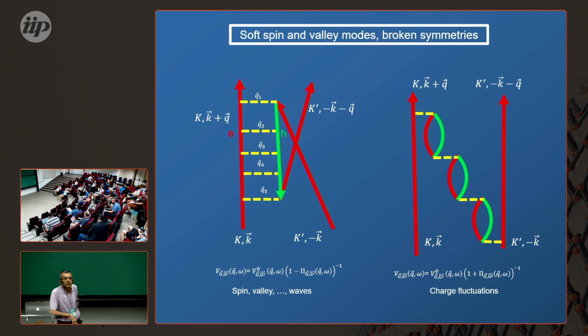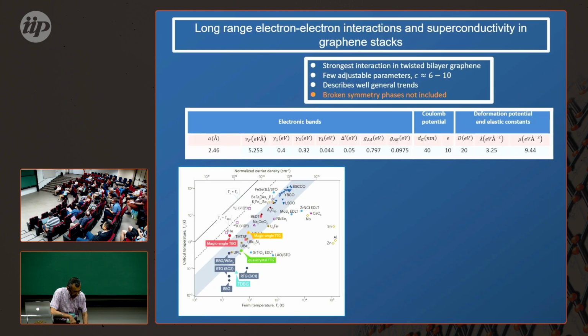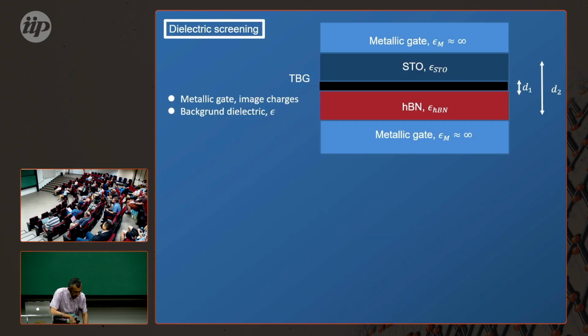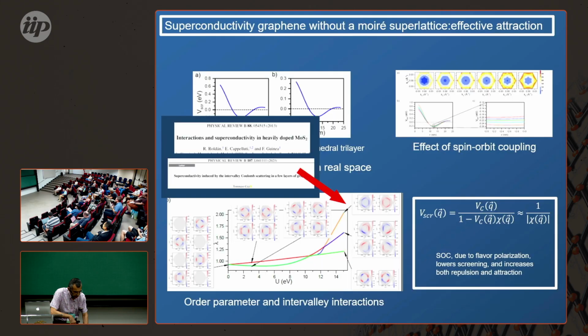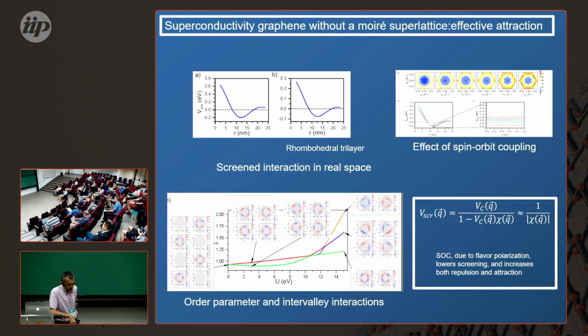So in your position-dependent interaction, you were showing there's a particular distance where there's attraction developing in your V of R, and I wanted to ask, what is setting that physical scale in the case of the non-Moiré system? So you're talking about non-Moiré systems? Yes, but you have shown the Moiré value. To tell you the truth, we don't know. This is probably related to the Moiré unit. I don't think it's 2kF Friedel oscillations because the Fermi surface is very distorted. It's near a Van Hove singularity, and the trigonal deformation is very strong. Oh, no, sorry, this is untwisted. It implies something for the response function. The response function is also anisotropic, so we cannot tell you. This is a good question.